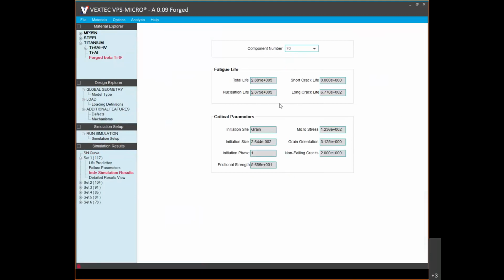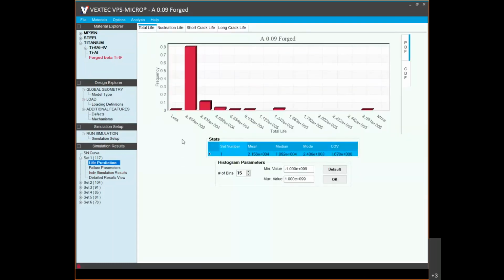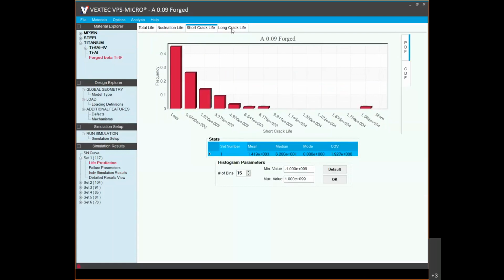I can also, for any one of these simulations, in the results section at the bottom of the software, click into the life prediction histogram of all 100 specimens of the simulation, and you can see a histogram of the breakdown of the total life, the short crack life, and the long crack life.